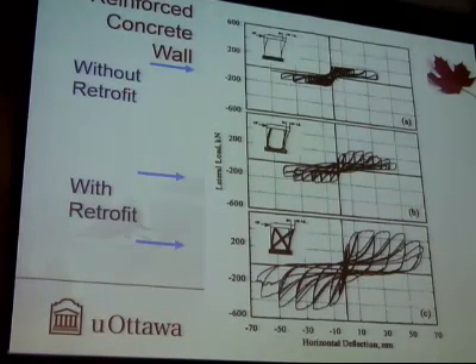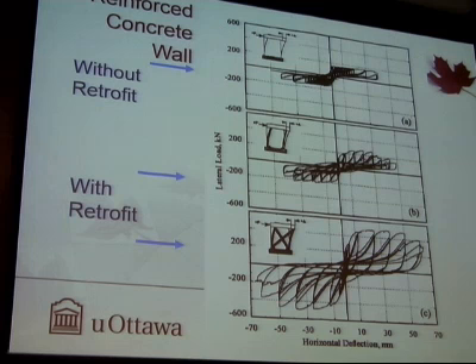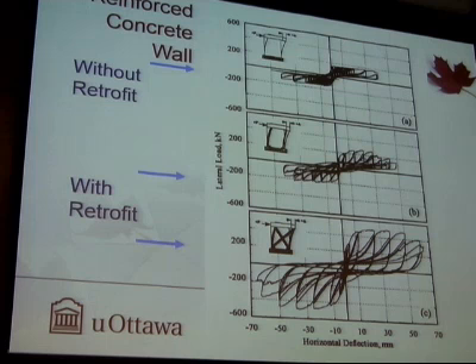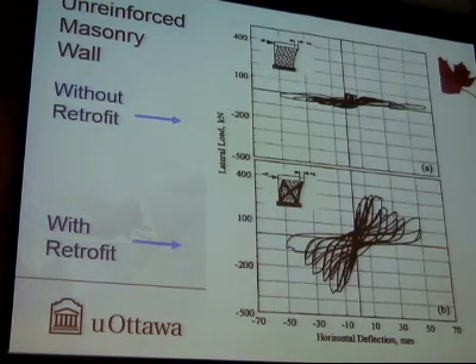Very quickly, the top hysteretic relationship shows a 1960s reinforced concrete wall, no boundary elements. The moment we pushed them beyond yield, longitudinal bars started buckling, and then it started virtually rocking along the wall foundation interface. But when we used these strips to provide boundary elements, there was some improvement, but further improvement was attained when we provided strips by means of through bolts along the diagonals as well.